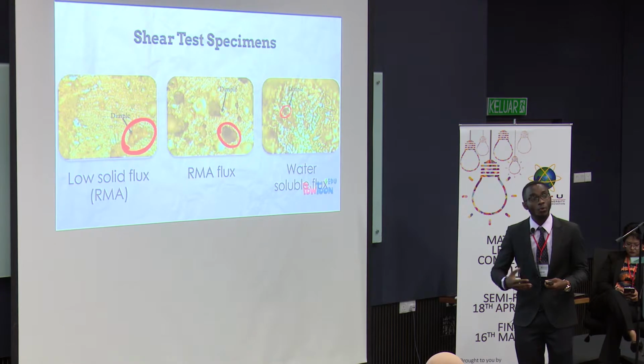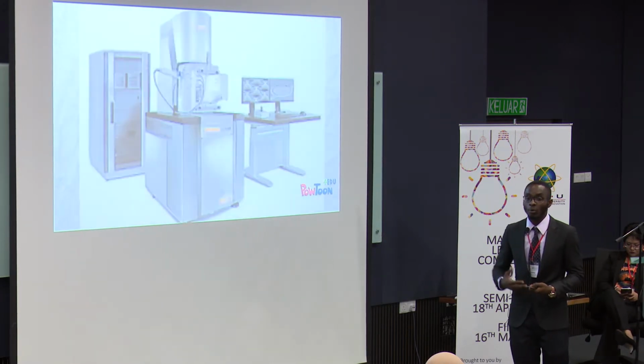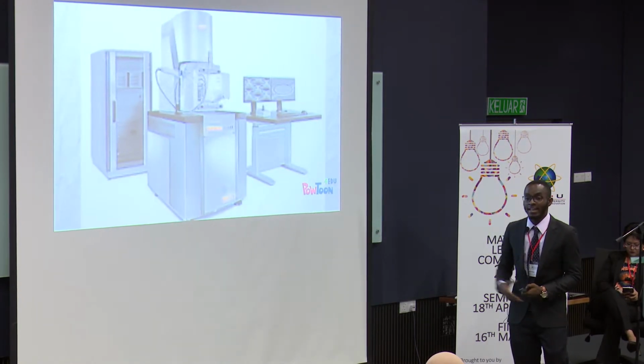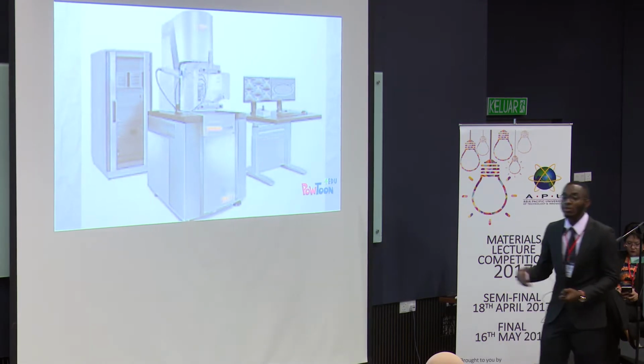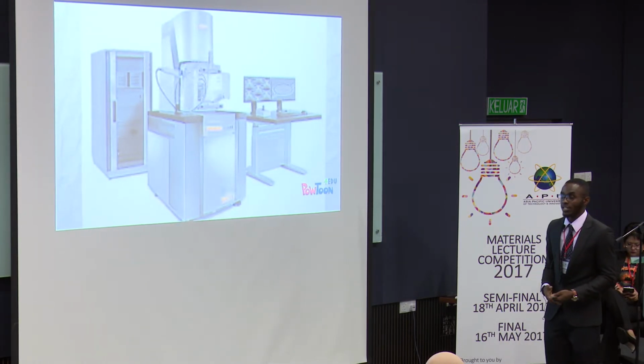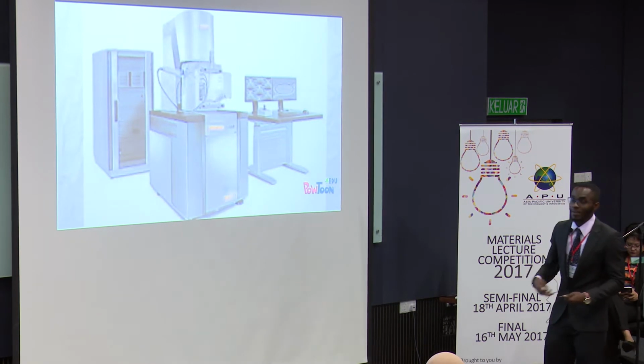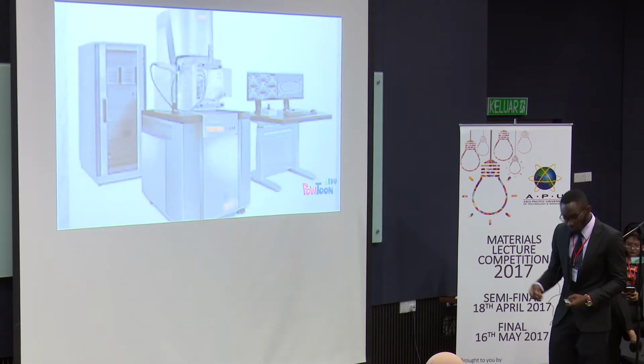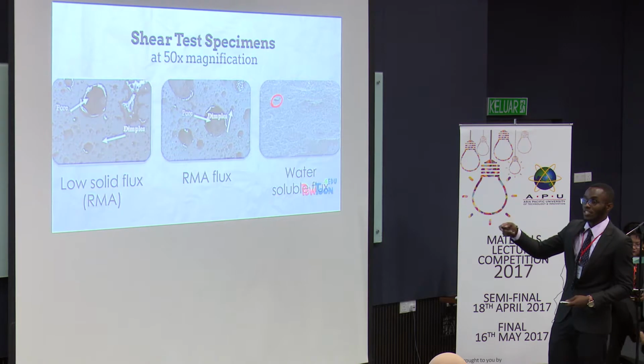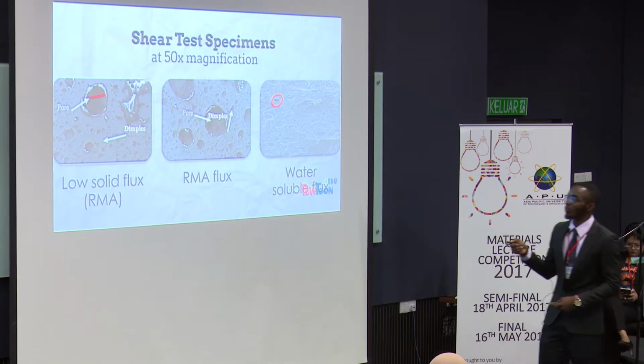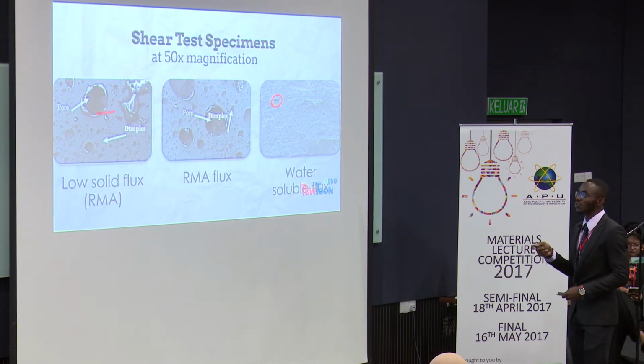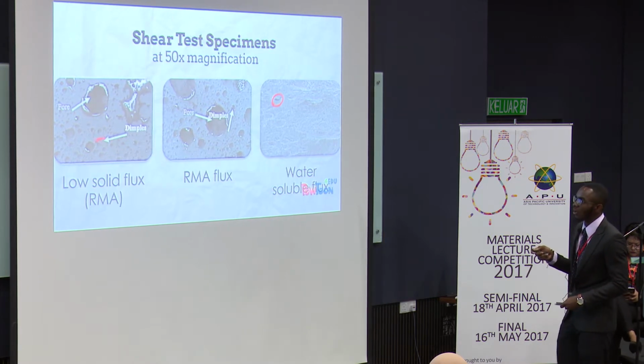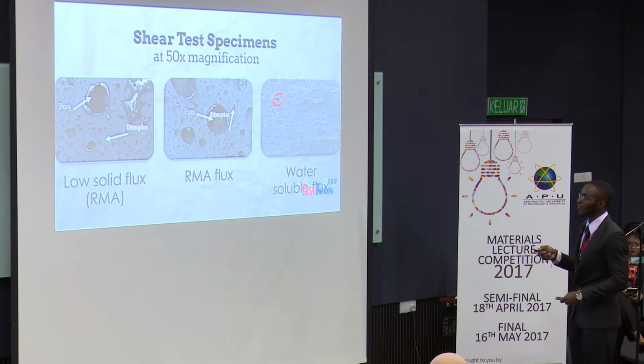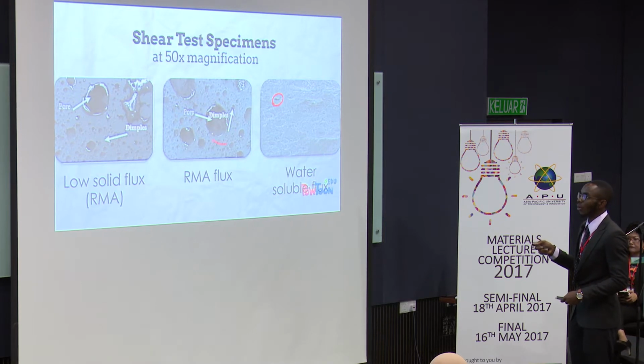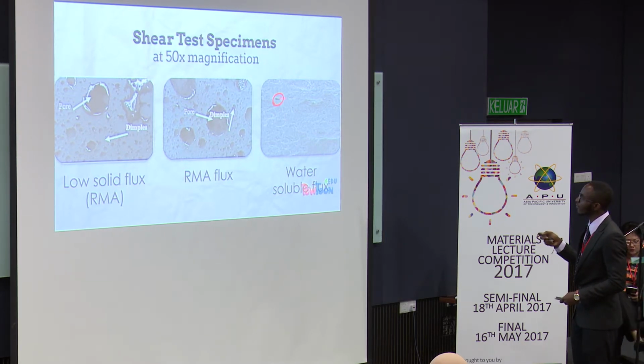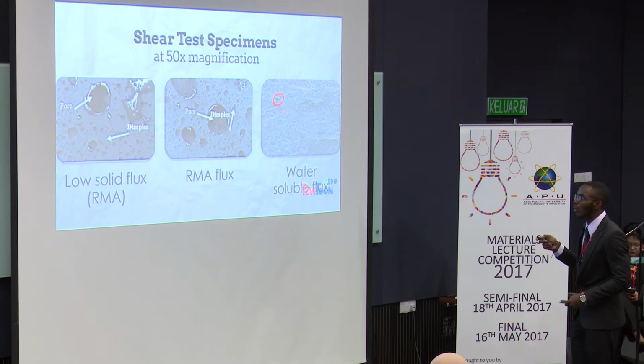Now we're more critical, so we incorporated a more sophisticated machine, which is the SEM, scanning electron microscope machine, to go deeper into the surface of the materials. Now at 50 times magnification, we can then view the surface of each of these specimens. Now we can see the pores on the low solid flux, which is quite huge. And we see dimples on the surface of the low solid flux. Similarly, a large pore on the RMA flux, but the water-soluble flux has the smallest pore on its surface.